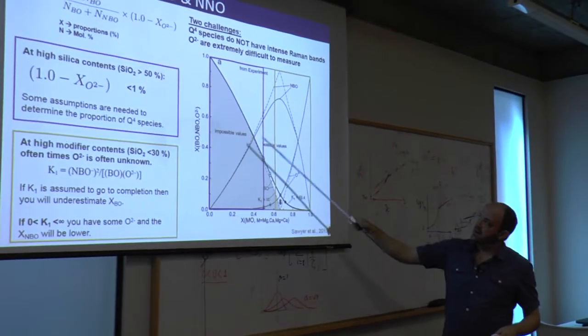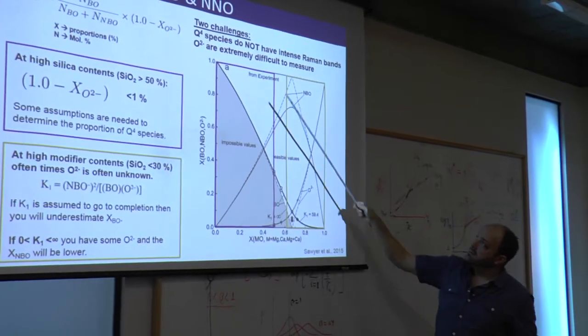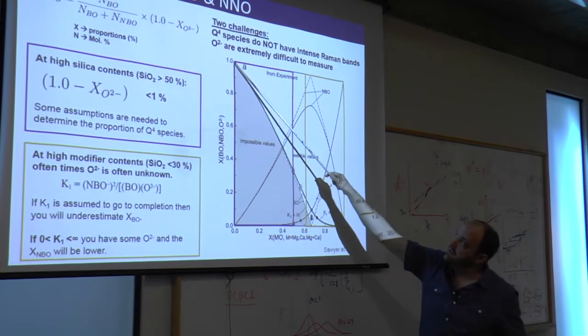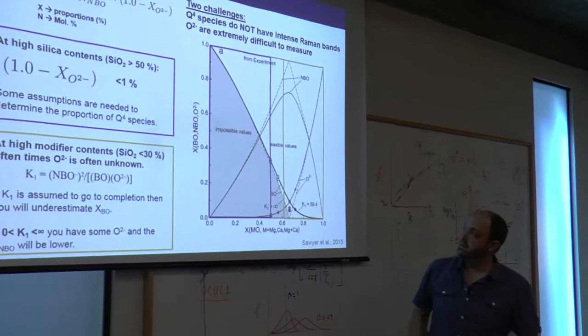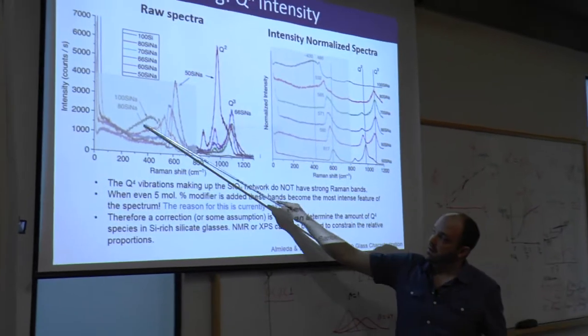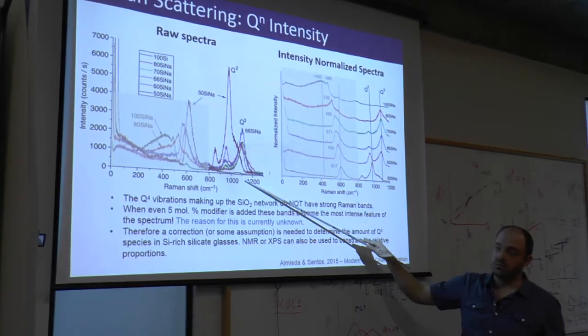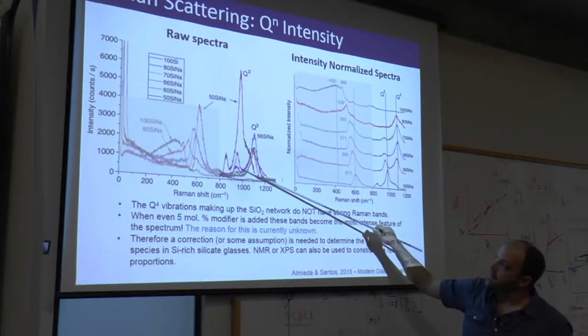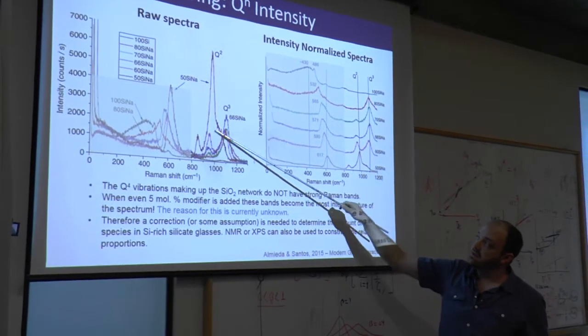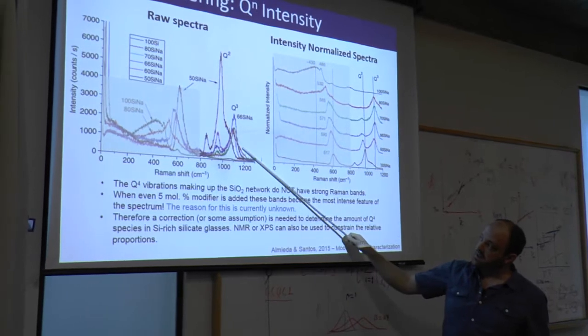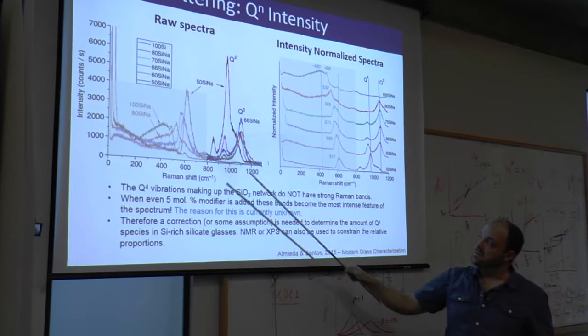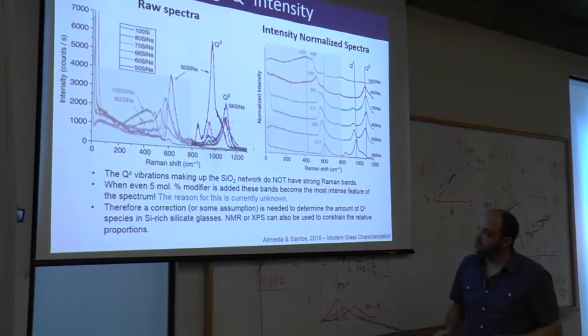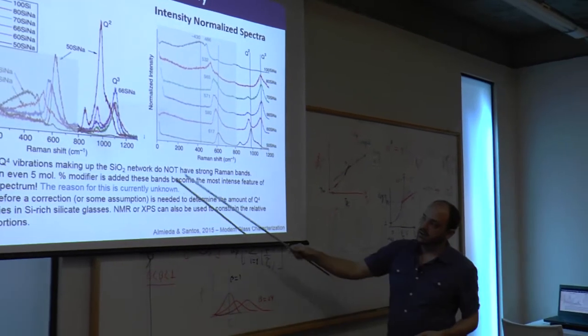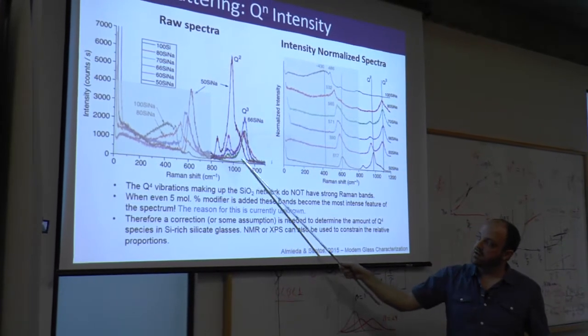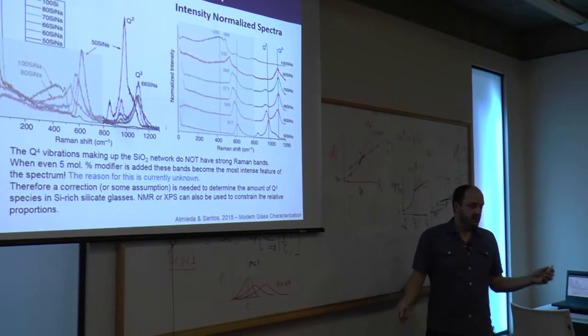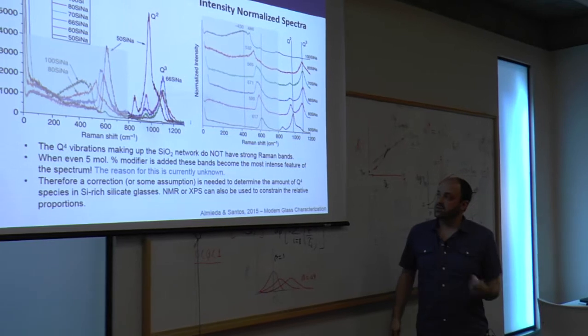On the other end of the spectrum, when you have silica-rich glasses, the problem is with the Raman intensity bands, and that's because of these Q4 species. We saw in silica that in the high frequency range, and I'll show this now, in pure silica, we have almost no vibrational modes. But as soon as we add even a little bit of sodium, we get quite strong peaks here, and these are the antisymmetric vibrations associated with the different Qn species, Q4 being at the highest frequencies and Q0 at the lowest frequencies. So there's a problem here. With Raman spectroscopy anyway, you can with NMR, but with Raman you can't actually determine the proportion of Q species directly from the spectra. You have to make some assumptions about the behavior of those Q species in your spectra.